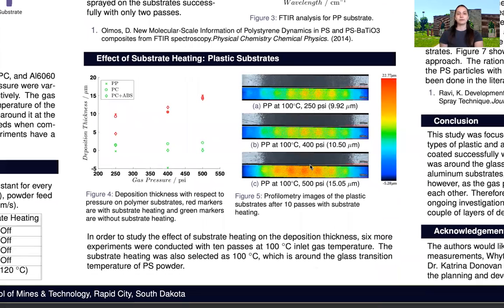Now that we were sure that we coated polystyrene on the surface and picked the gas temperature, we wanted to observe the effect of substrate heating. For this, we conducted 2 sets of experiments with 10 passes with and without substrate heating. Figure 4 shows the deposition thickness of polystyrene at different gas pressures at 100-degree gas temperature. As you can see, the deposition thickness increases with the gas pressure when the substrate heating is on. So for the plastic substrates, we concluded that when we kept both the gas pressure and the substrate heating around the glass transition temperature of polystyrene, we successfully coated them.